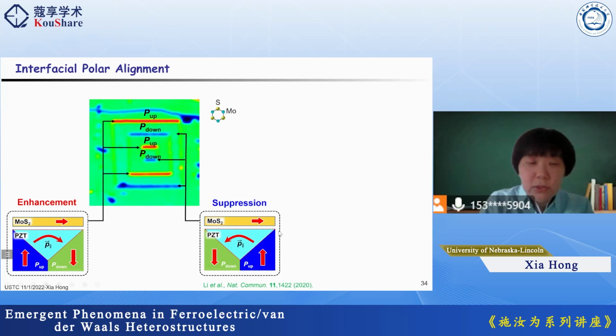So we use electromagnetic theory to model the second-order tensor for the SHG signal, and we find that this explains the enhancement and the suppression. Surprisingly, this suppression of SHG signal is very effective. What's shown here is a crack that exposes the bare PZT, where we expect no SHG signal. And here, the tuning of SHG signal by the domain actually matches this. So this is a very effective cancellation.